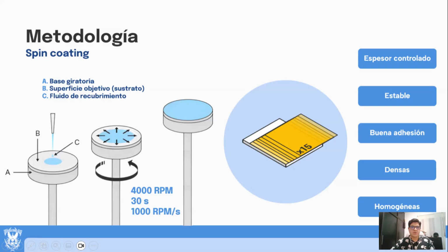Before deposition, substrates are rigorously cleaned via ultrasound in acetone, ethanol, and deionized water to remove organic contaminants and improve wettability. The sol is deposited onto the static substrate using a micropipette, then accelerated to 4,000 revolutions per minute for 30 seconds to achieve uniform thickness.